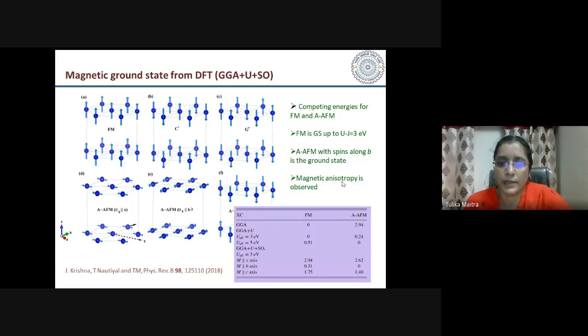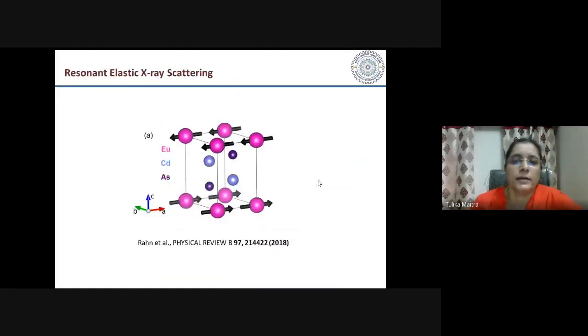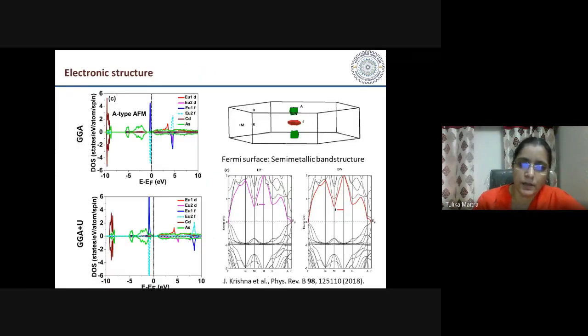And there is a magnetic anisotropy, and what we find is that the ground state is actually A-type antiferromagnetic, but the spins do not point along the C direction, they point along the B direction. This was our observation, and then this experiment came, this resonant elastic X-ray scattering experiment, and they indeed found exactly what we observed from our calculation, that the spins are lying in the AB plane, not along the C direction. And one can actually do the electronic structure calculation, and what one sees is that the electronic structure is semi-metallic in nature with electron and hole pockets.